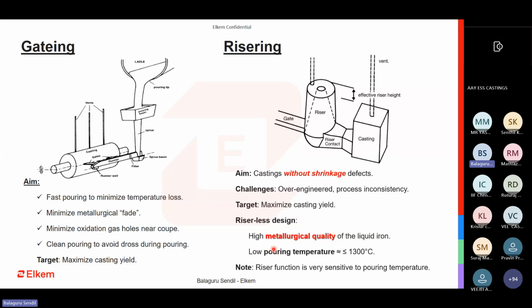And why the shrinkage happened in the first place is something that an RCA should properly address. And I think you can approach us, or you can take knowledge from the upcoming slides on how we can optimize it. So gating and risering. Gating is very simple. The objective is to fill the metal as fast as possible, as non-turbulent as possible, and ensure there are no gas defects. And when it comes to risering, shrinkage elimination, we should opt for very small risers and see if there's a possibility to eliminate them completely.